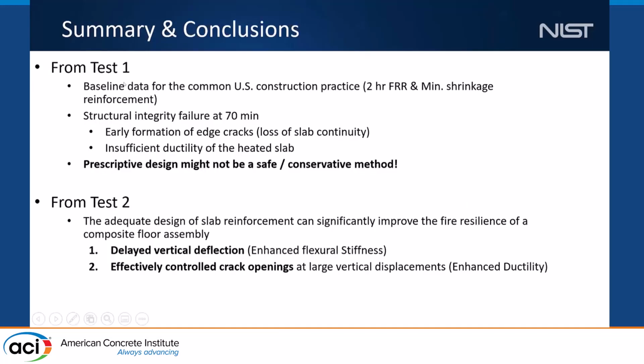So in summary and conclusion, test number 1 was aimed to create baseline data for common US construction practice. We utilized a 2-hour fire rating for the specimen design, and also included the minimum shrinkage reinforcement. Even though the specimen was designed for a 2-hour fire rating, we observed that structural integrity failure was reached around 70 minutes into heating. This is mostly because of the early formation of the edge crack that allowed the large edge rotation of the slab, and also insufficient ductility provided by the wire mesh mat in that particular specimen. So this experiment provides very good experimental evidence that prescriptive design is not always a safer and more conservative method.